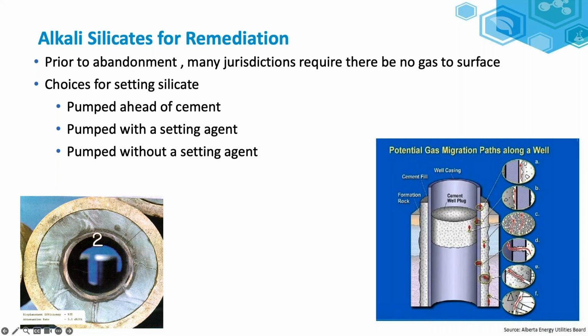And over the years, lots of different systems have been developed for the placement of sodium silicate. Silicate plays very well with cement. So if they come in contact, the cement will set up the silicate. So one tried and true method is to pump a silicate solution followed by spacer, then cement. So the silicate leading into the very fine fractures, high perm zones, followed by the cement. And when the cement does come in contact, it sets up.